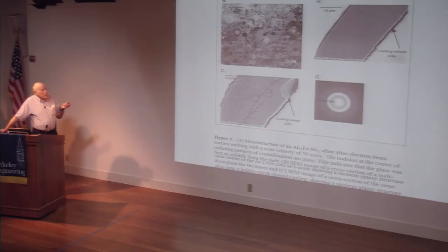More than that, this glass rejected aluminum into the melt, and on higher resolution you can see a thin band that is mostly aluminum before the eutectic sets in. So there's coexistence with partitioning, and that's a hallmark in multi-component system of a first-order transition. So this glass formed from the melt by a first-order transition.